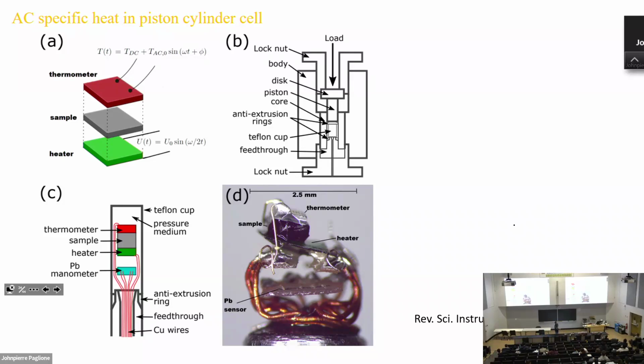So the DC is hard to measure because you have all of the other liquid. It's hard to get an absolute value, but you can do AC specific heat. For details, you can refer to this paper. Basically, you put a heater there, you have thermometers, and you apply an AC current to the heater and detect the change in the thermometer. So here's the setup. You can see the sample on the heater and the thermometer.